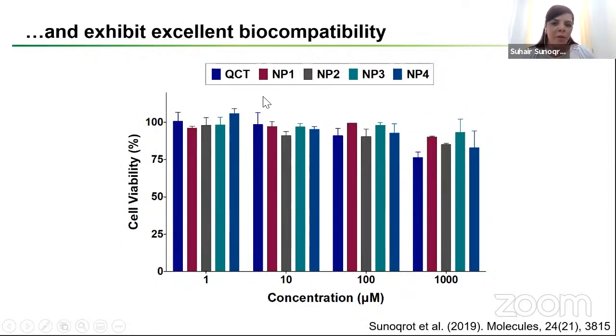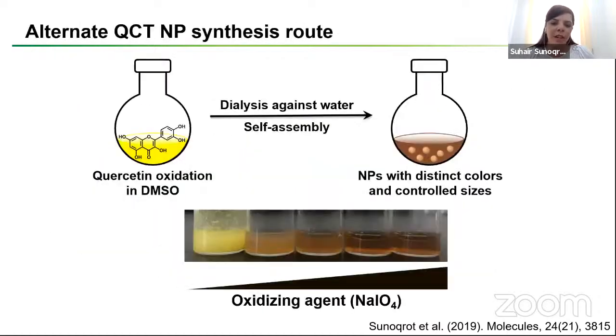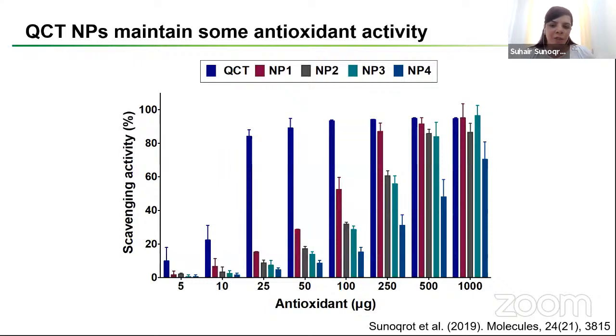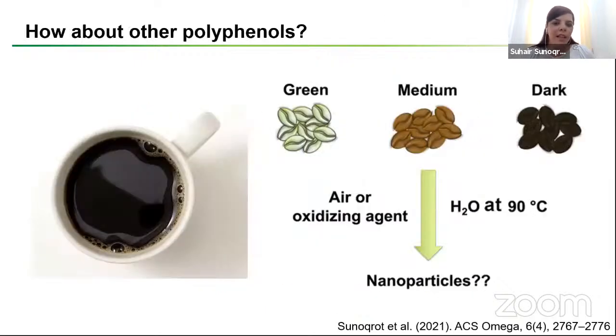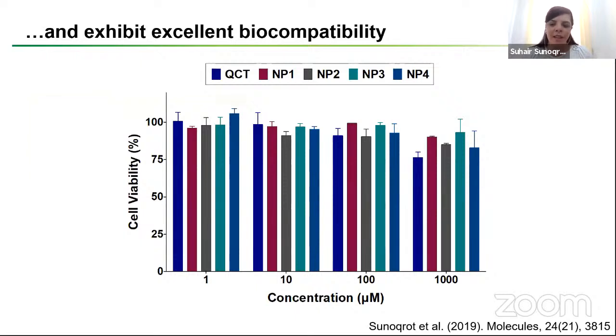And we tested their biocompatibility with human dermal fibroblasts, and they were very biocompatible. So we think maybe they can be useful for cosmetic preparations because their color resembles the skin tone color. So we can apply them on the skin as antioxidant or UV protective nanoparticles because they can absorb in the UV region. And so that's the story with quercetin. As you can see, we were able to obtain a lot of interesting results from it.